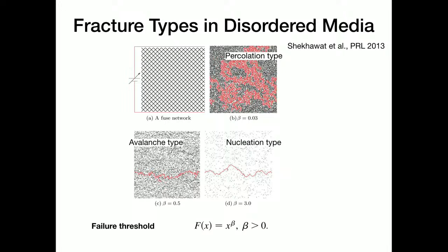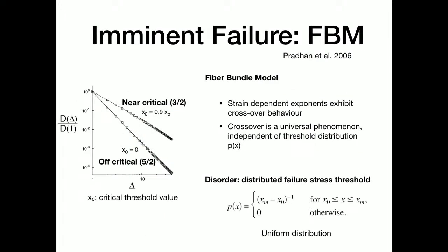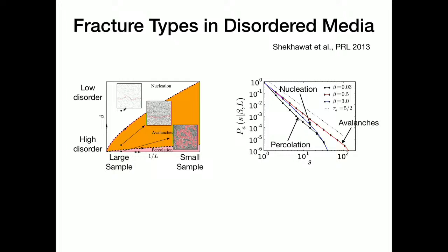I think it will come, but quickly if I answer that, here there is no pre-existing macroscopic crack per se. So Griffith's criteria is not really applicable. It's a disordered medium, everything is intact, but the strength is distributed. So when you are pulling it apart, there will be some nucleation events. Of course, the nucleation events would result in localization of stresses and strains, in random spring network at least, I don't know the exact mapping. Exactly. Okay. So that is related to the avalanche statistics.